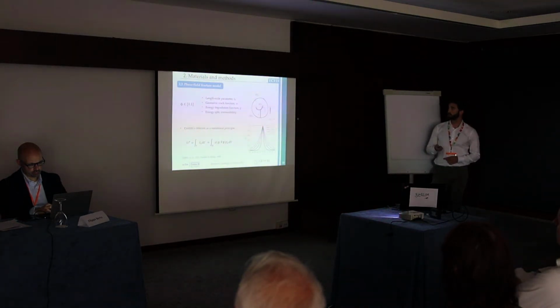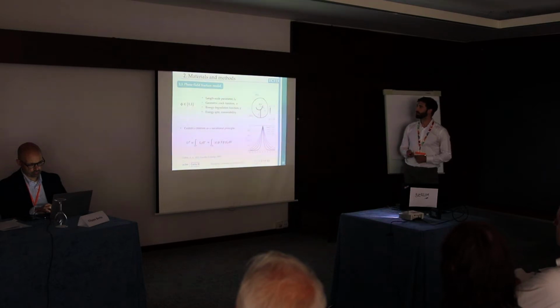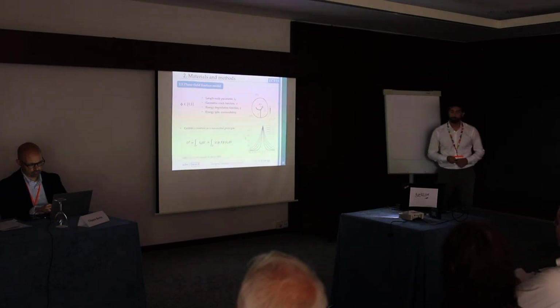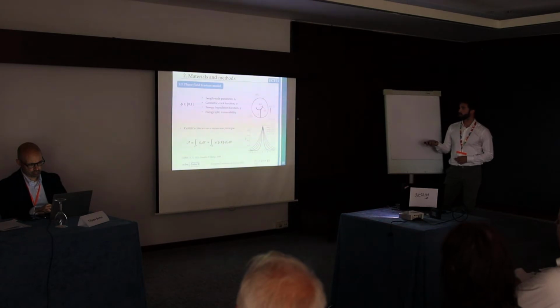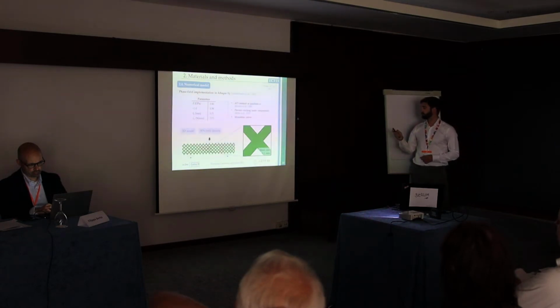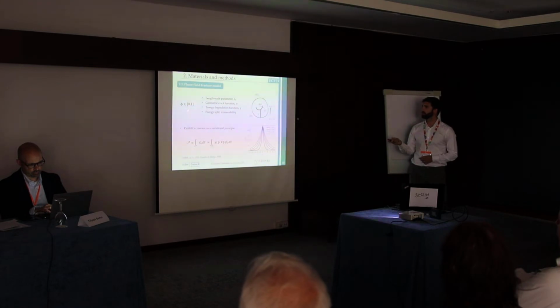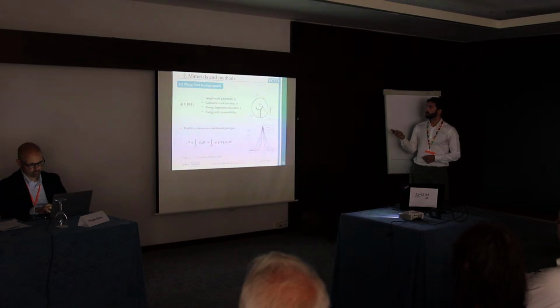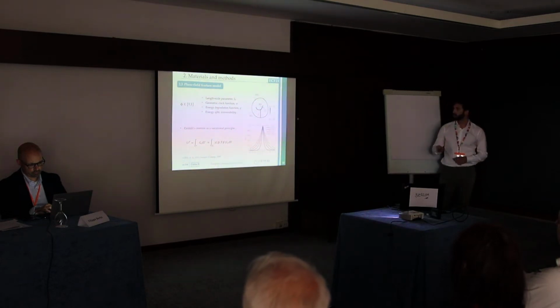Okay, so as I told you, we used a phase field fracture model for the prediction of the failure. As a brief summary, we use a continuous variable phi going from 0 to 1 to describe the nucleation and the growth of the crack. Okay, so 0 means that there is no damage in the material, and 1 that the material is fractured.